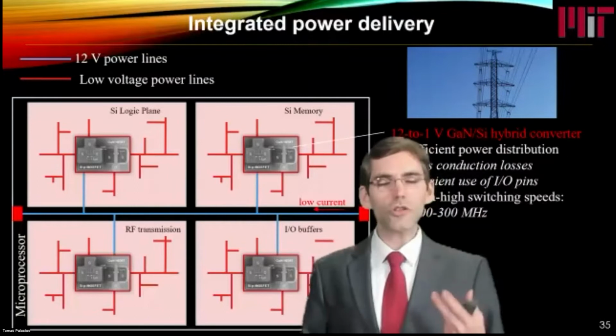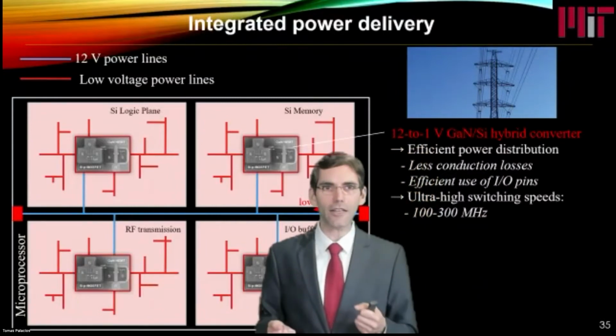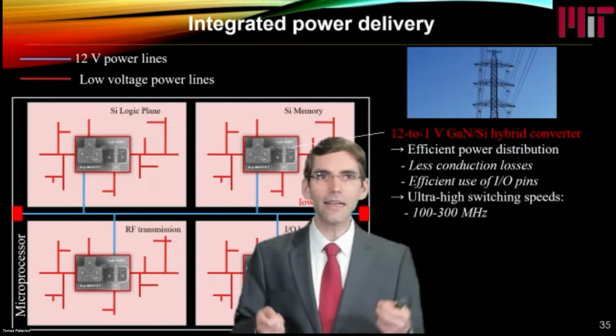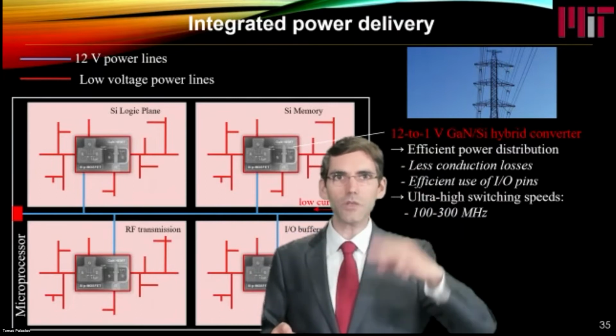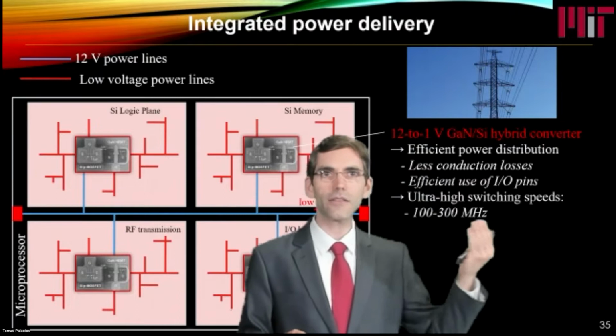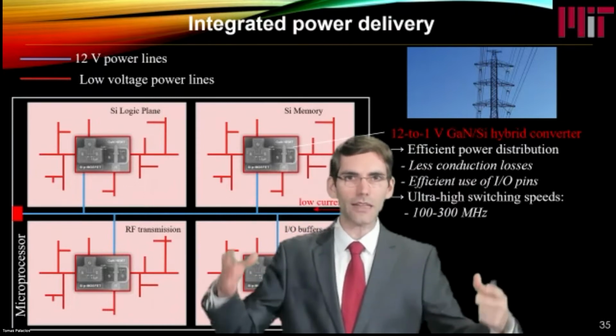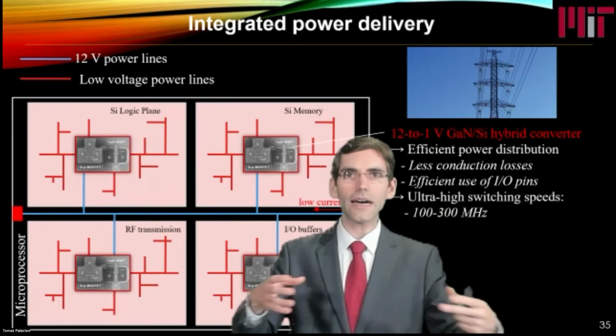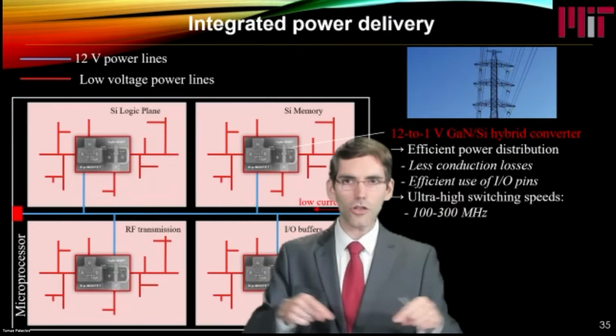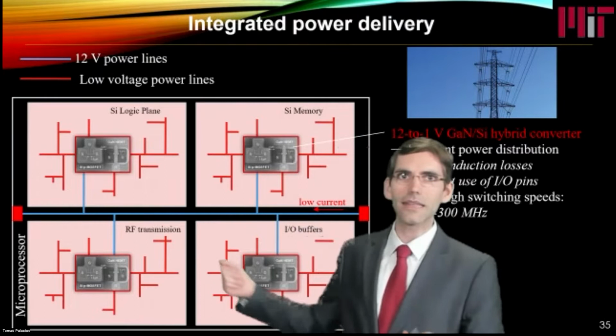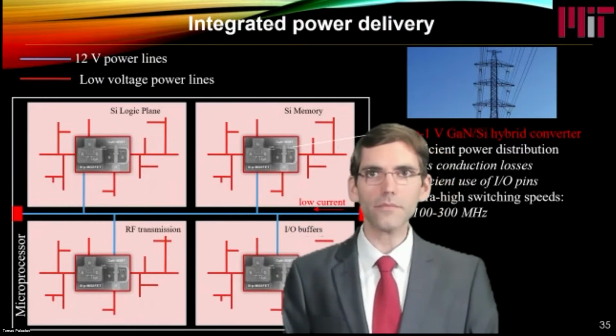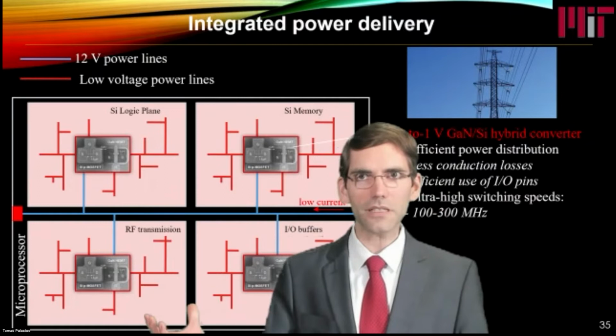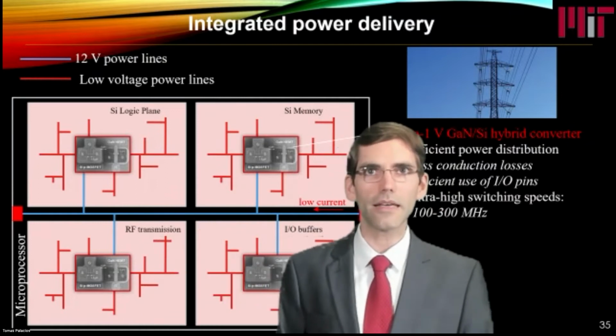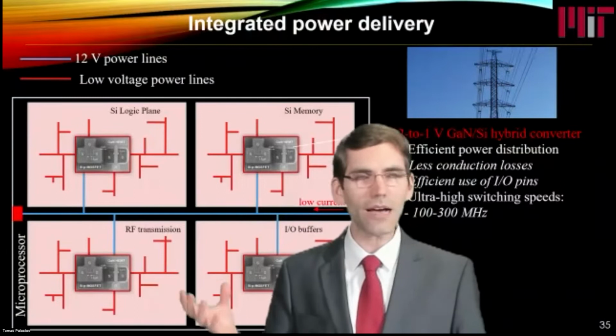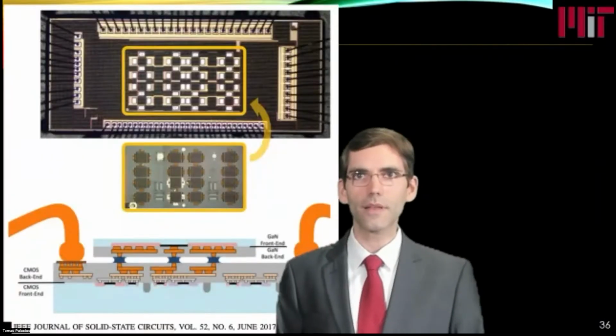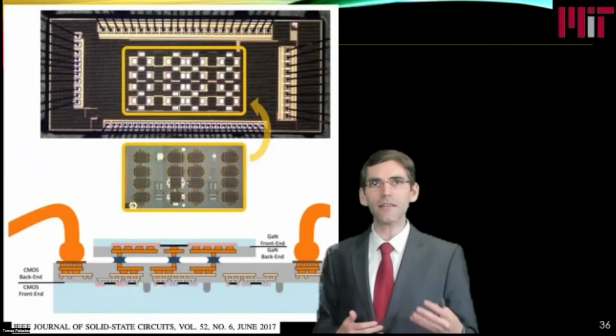For this, we need to use wide bandgap semiconductors like gallium nitride, because this is the only material that allows you to have very high switching frequencies, in the order of 100 to 300 megahertz, to make sure that the power converters that you need are small enough to not use too much real estate in the microprocessor. So in the future, every microsystem will have a gallium nitride power unit integrated, one or hundreds. And we are prototyping this in many different ways.